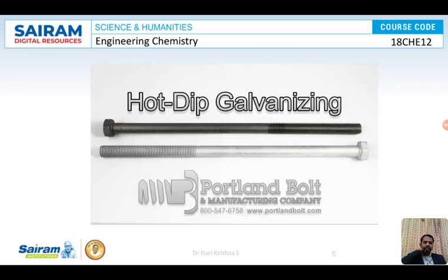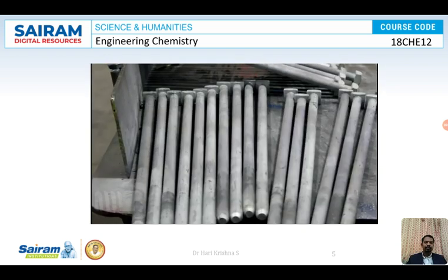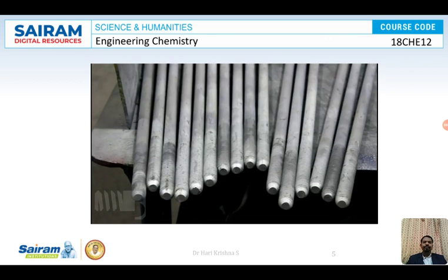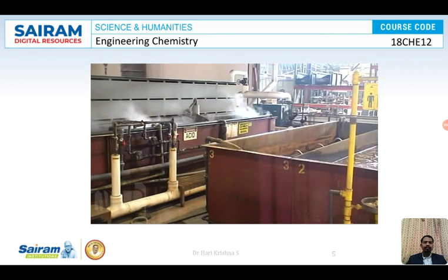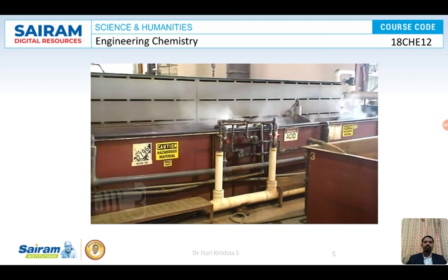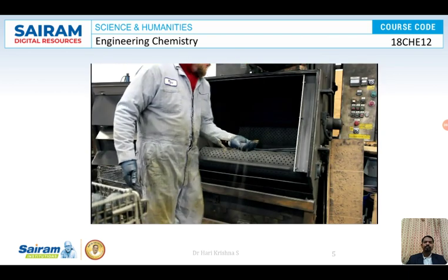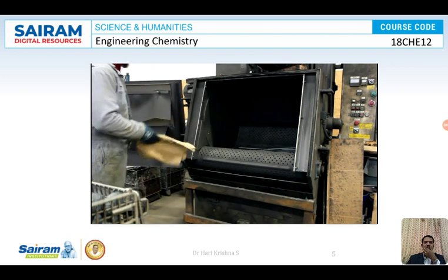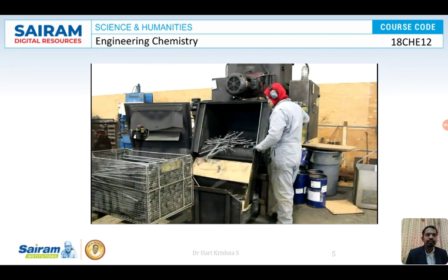Galvanizing is the process of metallurgically bonding zinc to steel to prevent corrosion. The challenge in galvanizing bolts is preventing zinc buildup in the threads, which can prevent nut assembly. Portland Bolt uses a specialized galvanizing process to ensure clean threads. Some bolts are blasted with steel shot to remove the excess forging, heat treat, or mill scale that can prevent the zinc from bonding properly with the steel.